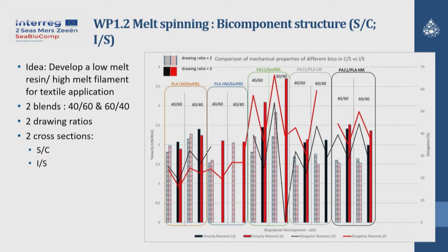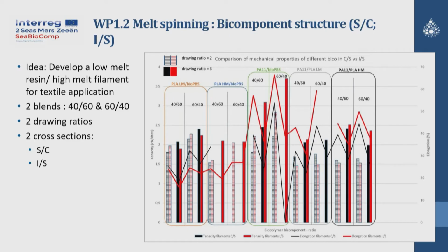For core-sheath, PA11 with bio-PBS seems to be the best couple, but not obvious. It's more obvious if you look at the islands-in-the-sea structure. In melt spinning, in general, it seems to be the more appropriate structure if we look at the tenacity.